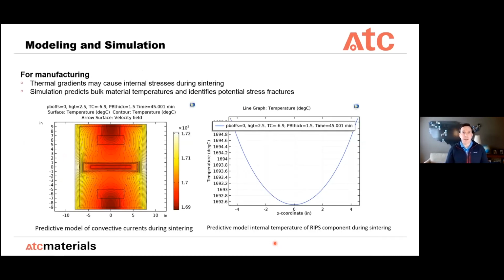I mentioned the modeling and simulation that we do for armor. We also do quite a bit of that in our material preparation. Because these are complex and high value parts, there's a significant benefit in predicting their behavior before you manufacture them. And so that can certainly also be used to predict the manufacturability of the part. So on the left, the orange image represents a part in a furnace, and we can take a look at the temperature gradients within the furnace to identify the heating effects on the part. And then the parabola on the right represents the temperature deviation from the surface to the center line of the bulk of a part.